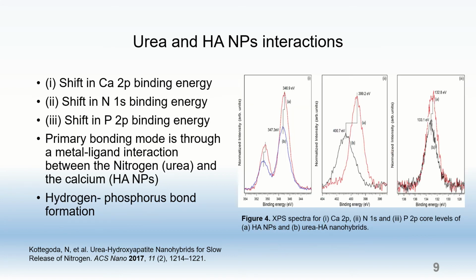Now, the interactions between urea and hydroxyapatite nanoparticles were further studied using XPS, which is shown in figure 4, where the calcium 2p, the nitrogen 1s, and the phosphorus 2p binding energies were monitored between pure hydroxyapatite nanoparticles and the urea-coated hydroxyapatite nanoparticles. Now, the most significant shift in peak position towards higher binding energy was shown here in figure 4, and it corresponds to the nitrogen 1s core level for the urea-coated hydroxyapatite nanoparticles.